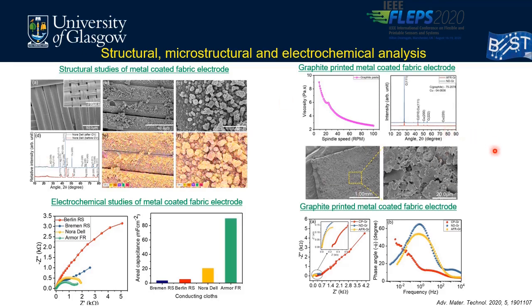From the graphite coated electrode, we can clearly see the highly porous structure of the graphite electrode. This is responsible for high EDLC capacitance formation. The viscosity of the developed graphite ink as well as the XRD analysis of the graphite coated electrode are also given in the image. So the electrochemical studies of this metal coated fabric show two fabrics, namely Noradel and Armor FR, show the highest areal capacitance among all the 4 fabrics under investigation. So we optimized, or we finalized, these 2 fabrics for further investigation.